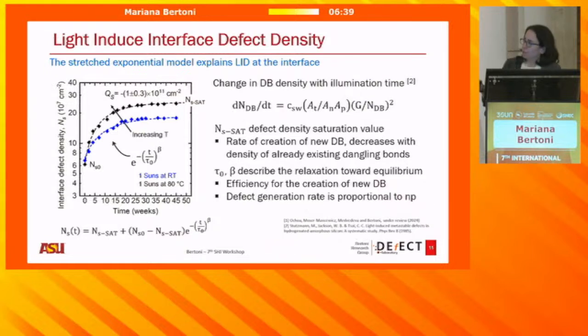So a quick comment here on the change that we observe of dangling bond density at the interface with illumination time. This is nothing really new. This was proposed by Stutzmann back in the 80s. But your NA, the saturation level for your defect density at the interface, is basically the rate of creation of new dangling bonds, which decreases with density of already existing dangling bonds. So basically, the more you have, the less you create, which kind of makes sense.